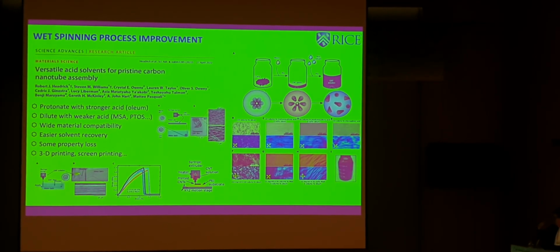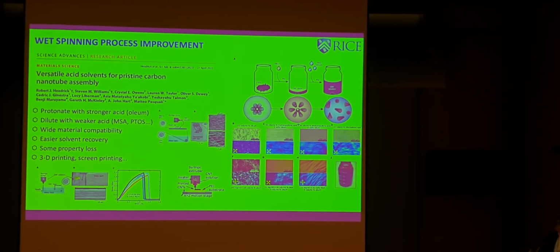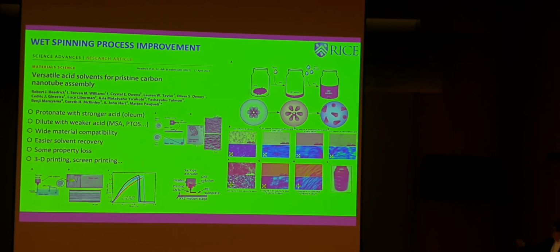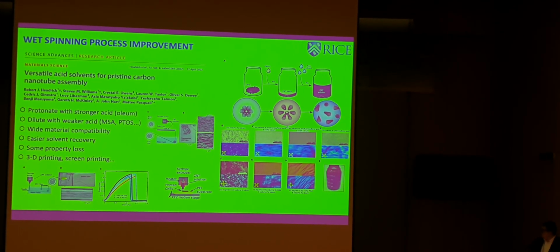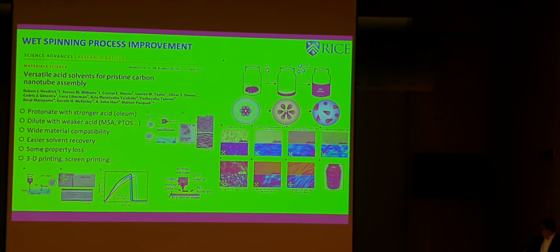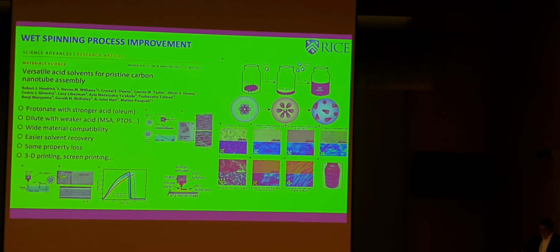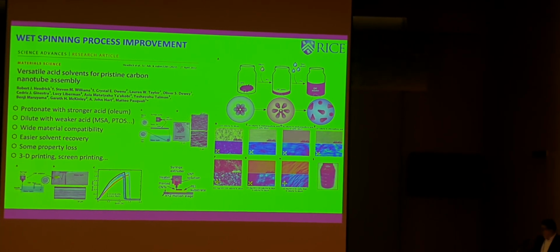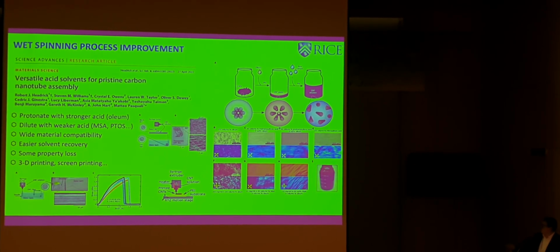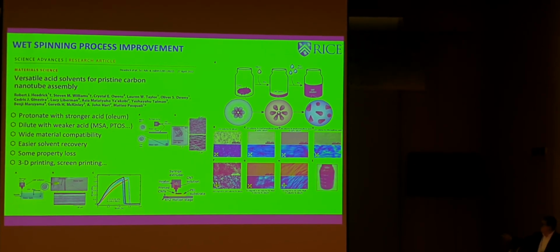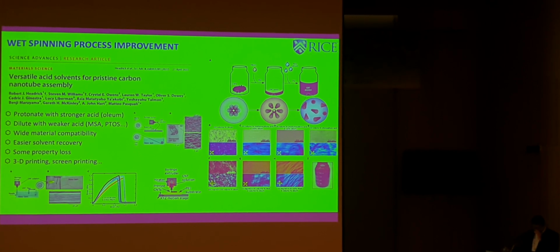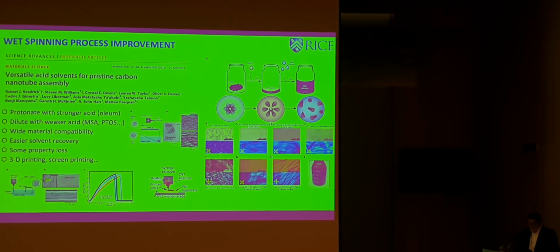This was my team, mostly the PhDs, Robert Hedrick, that showed that if you pre-soak the nanotubes in a strong acid like oleum, then you can get the liquid crystal even in a weaker acid, and then this becomes drop-in for doing things like screen printing, 3D printing. You can coat these on PET, etc.